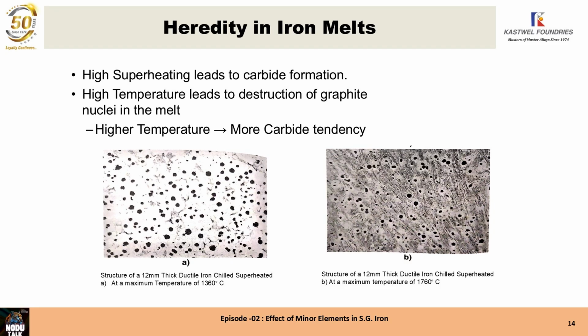If you superheat the metal, like in slide B, it is superheated to 1760 degrees. You see all those structures between the graphite nodules, they are carbides. They are very, very strong carbides. Sometimes these carbides cannot be annealed out by high temperature heat treatment process also. So never superheat the metal, and never hold the superheated metal at high temperature for a long time.